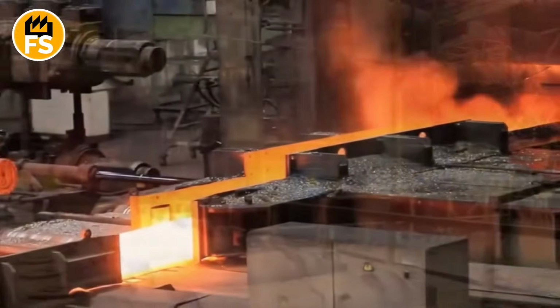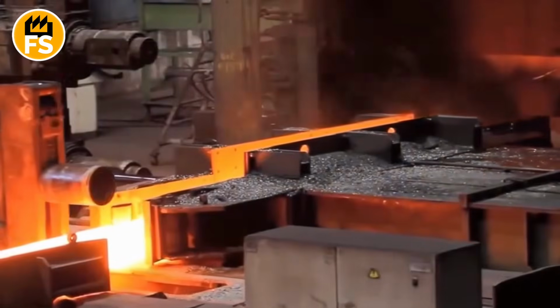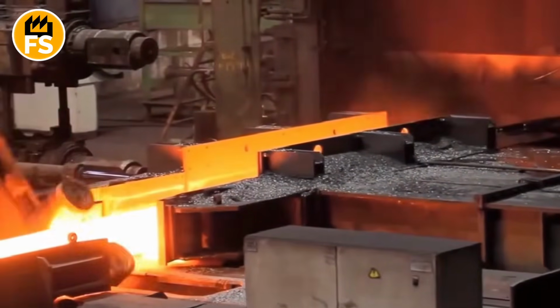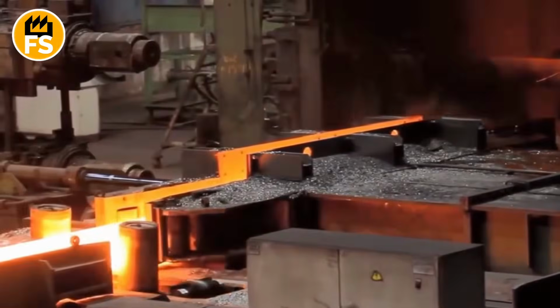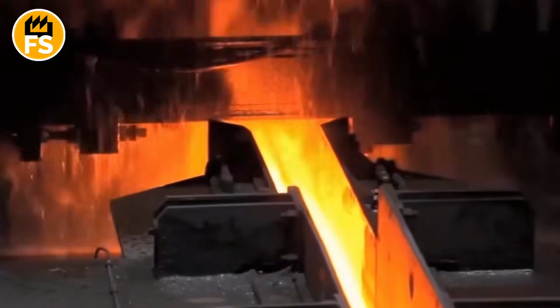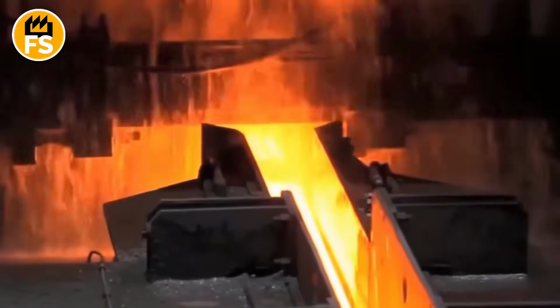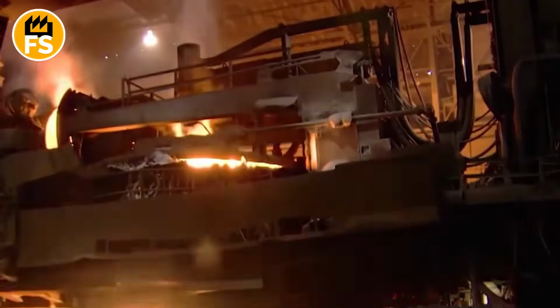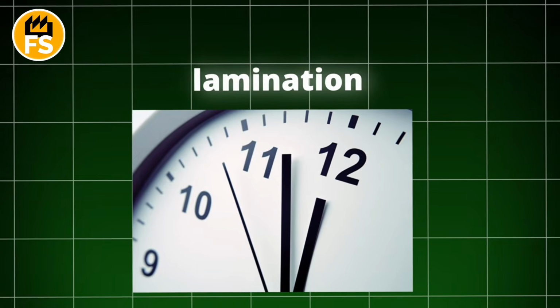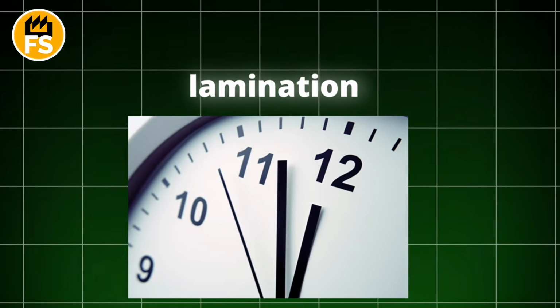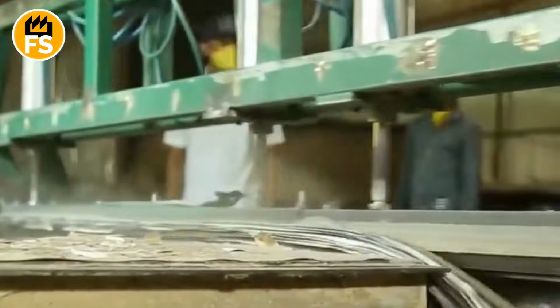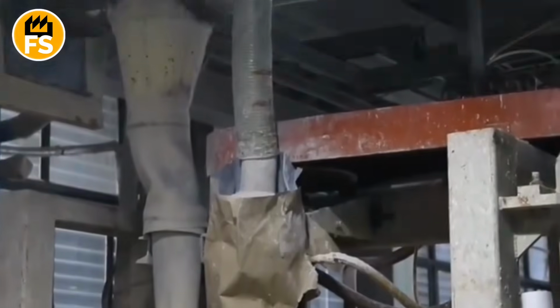This multi-layer structure is placed in a press where, under the influence of high temperature, which can reach 420 degrees Fahrenheit and a pressure of 1,200 pounds per square inch, the melamine resins melt and harden, securely bonding all the layers together. This process takes from 30 to 40 seconds and is called lamination. During pressing, the surface texture is also formed, which can imitate the texture of wood. After pressing, the laminate sheets are cooled and stabilized, which is important to prevent deformation.